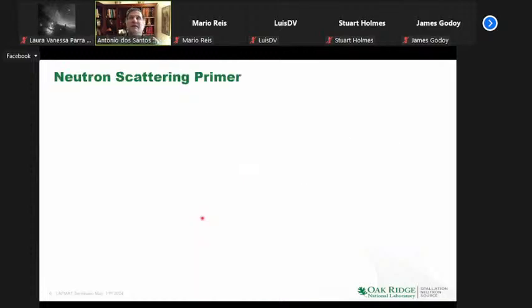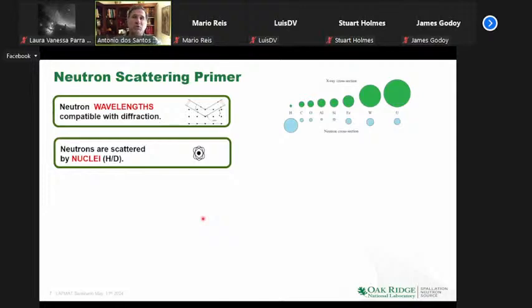So first, a little bit about neutron scattering, like what is it from our side, from the material science part. First, you can produce neutron beams with wavelengths, and these wavelengths are compatible with diffraction. So we're talking about from 0.5 angstroms to 2 or 3 angstroms. You can really probe atomic structures of materials. To be very clear, you can make beams with much colder neutrons, in which case you're going to explore much larger scales. So you can have SANS, small angle neutron scattering, and mu SANS, and you can go almost to the micron level of structures. What I'm talking about here is atomic structures, to be clear.